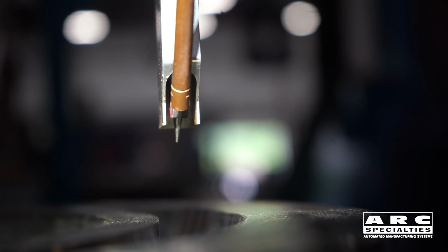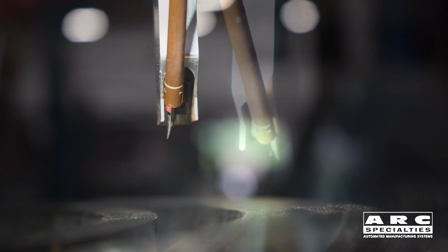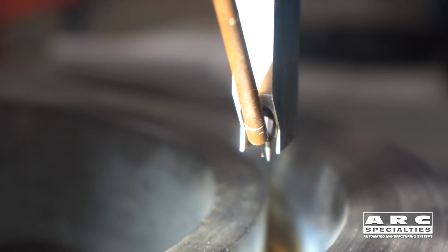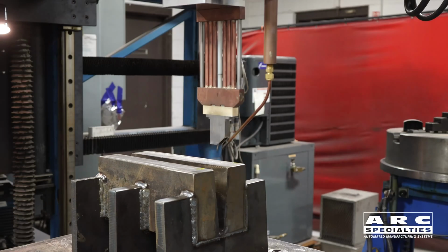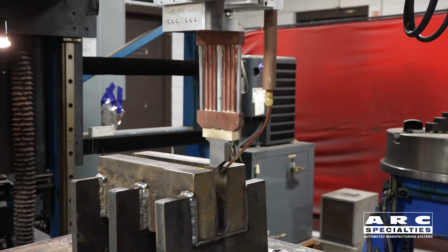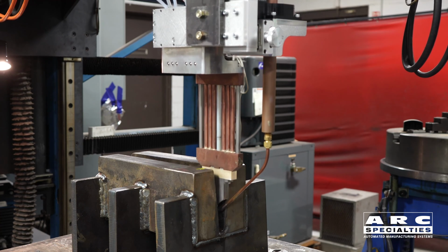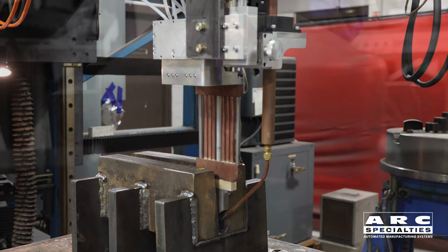And the second servo axis positions the wire, so you're able to sweep the torch back and forth across the groove, wetting the left wall, the right wall, and move the wire with it. It worked great, but we were limited to only around 4 inches in thickness. And once people saw what we're doing, they wanted to see how far we could push it. So we've come up with a deep hole torch that'll go down to a foot. What this means is with a two-sided groove, you can weld joints up to 2 feet thick. That's 24 inches. And with gas tungsten arc welding, it's not a fast process.